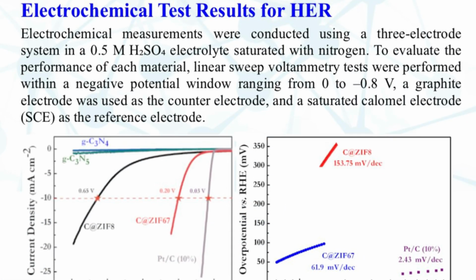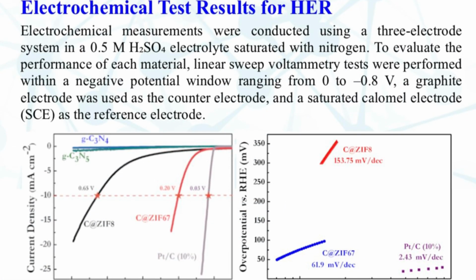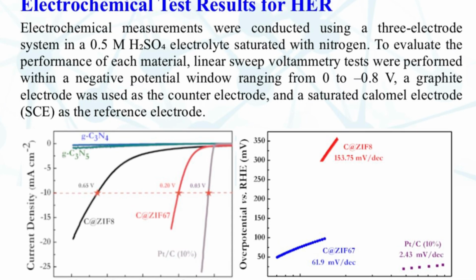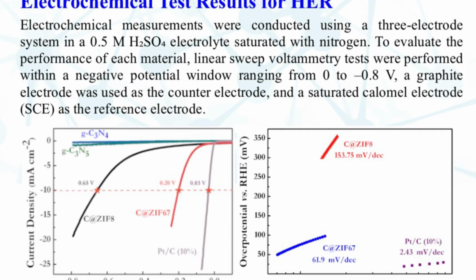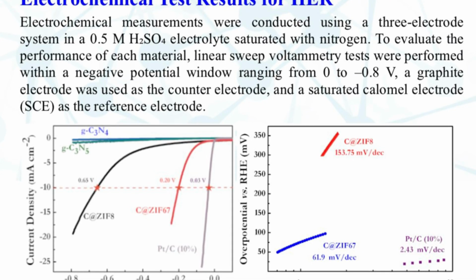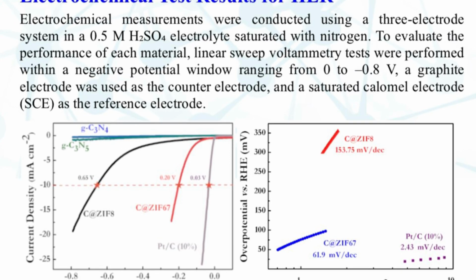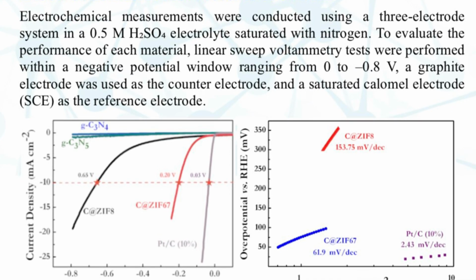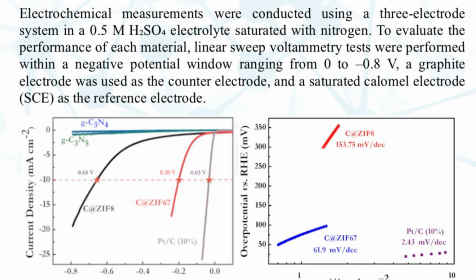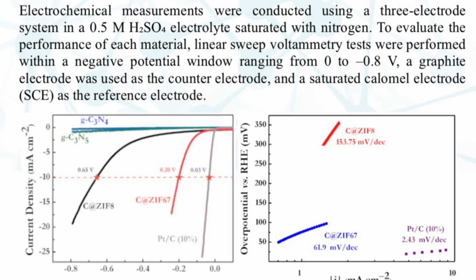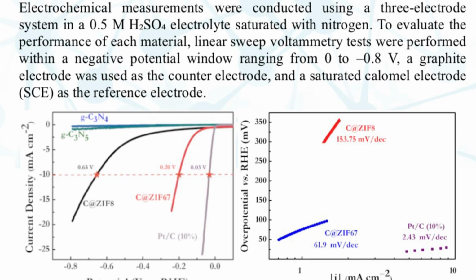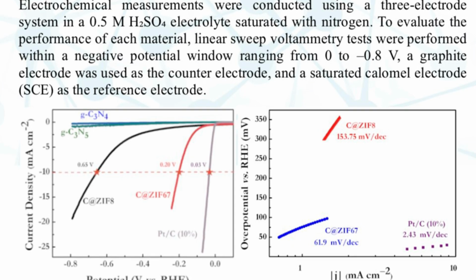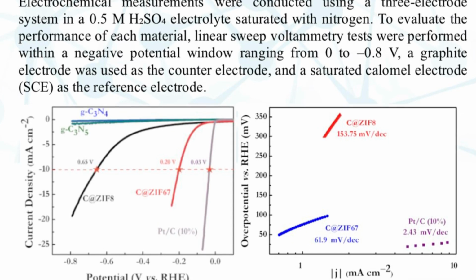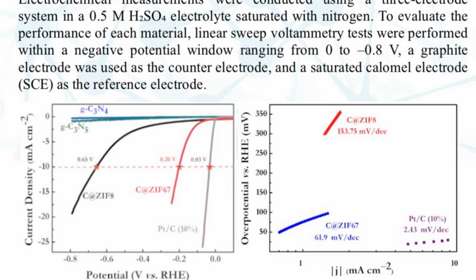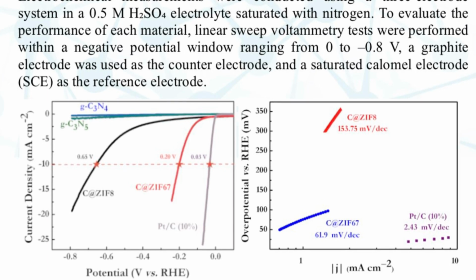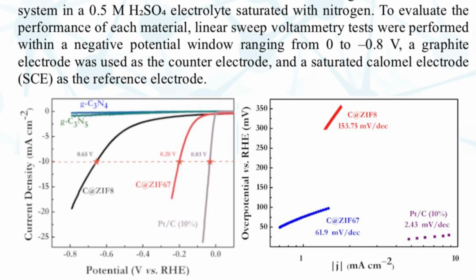For the electrochemical characterization through hydrogen evolution reaction, a 3-electrode system was used to carry out the electrochemical measurements of the as-prepared carbon materials in 0.5 molar sulfuric acid electrolyte. For estimating the hydrogen evolution performance of each of the materials, linear sweep voltammetry was recorded in a selected negative potential window from 0 to minus 0.8 volt, using a graphite electrode as counter electrode and a saturated calomel electrode as